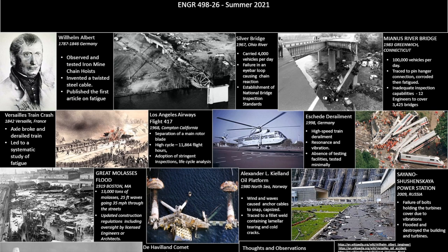Below that, the Alexander L. Kielland oil platform capsized in 1980 in the North Sea, Norway. All anchor cables snapped and the drilling rig capsized, causing the death of 123 people. Investigations into failure were traced back to a non-structural fillet weld containing lamellar tearing and cold cracks. The cyclic nature of the winds and waves alongside the poor weld resulted in fatigue failure of the supports.